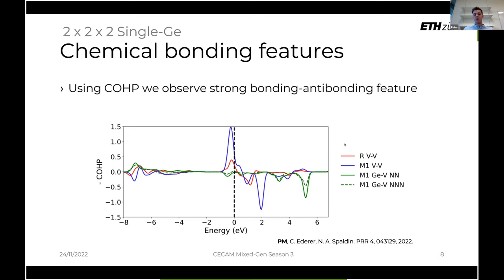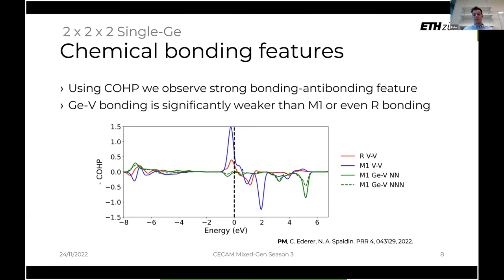And so in particular, if we first look at the monoclinic vanadium-vanadium bond, which is this blue line, we see that there is a strong bonding feature below the Fermi level and a strong anti-bonding feature around 2 electron volts above the Fermi level. This agrees very well with what is known about VO2, about having a singlet state, which is strongly bonding. However, what we also notice in the green lines is that germanium-vanadium bonding, with the full line being the nearest neighbor and the dashed line being the next nearest neighbor, is comparatively very weak.